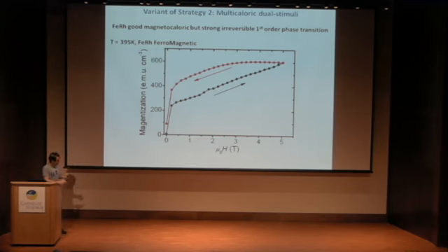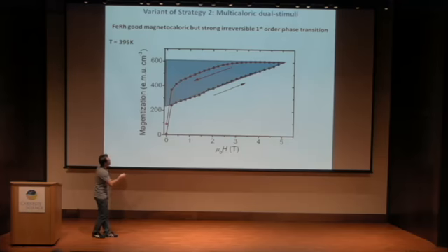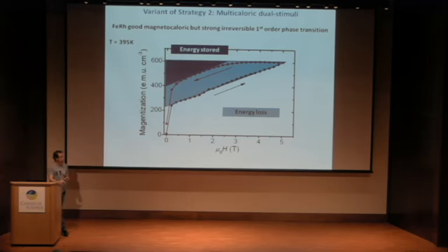So the idea here is the problem of the energy that you want to have. If you follow just the black one, the energy that you can store is exactly this one. But you have a hysteresis loop, so it means that all this part is lost. And you see that finally, the energy that you can extract from your system is very small compared to what you may expect at the beginning. So you need to find a solution to suppress, somehow, this hysteresis loop.